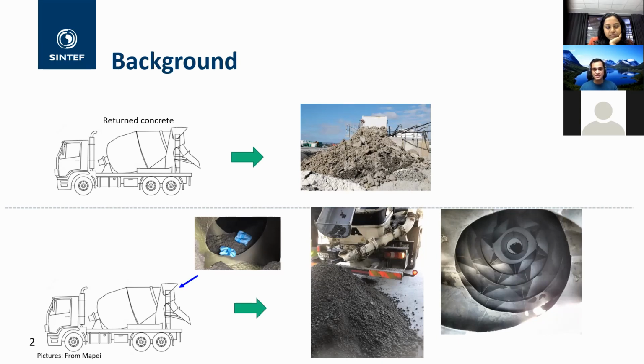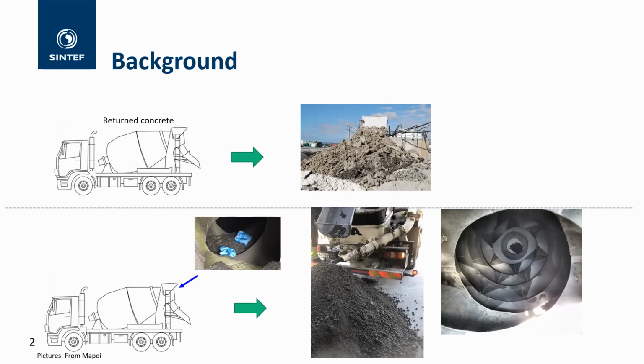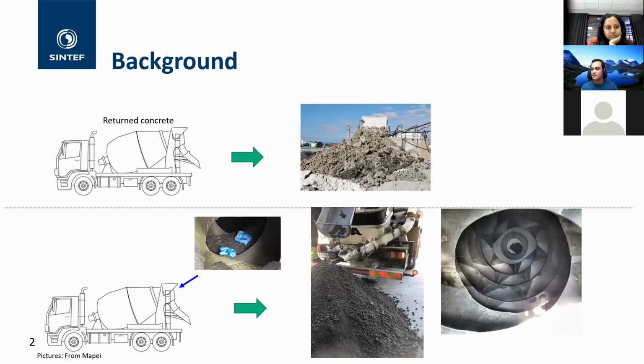So when we mix the return concrete with this product, after 3-4 minutes of mixing in the drum, we get recycled aggregates and a relatively clean drum without sludge. These aggregates can be used back in the production of concrete, used as a filler material, or can again be used for dry cleaning of the concrete drums. So next day or in a couple of days, we can add these to the concrete truck and mix them with the fresh concrete, and they will again make recycled aggregates, which is very good as it reduces the waste.